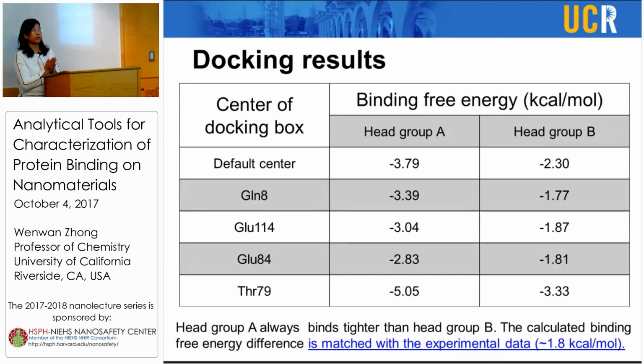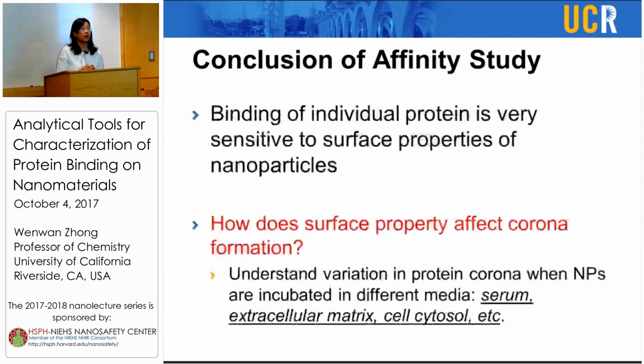head group B. So indeed, the simulation supports our observation that even though it's just a small head group structure difference, it could induce big differences in binding strengths. This is in particular true for proteins that can open up and form a relatively large interface with the particle. So a subtle change on the surface ligand could affect the binding greatly.